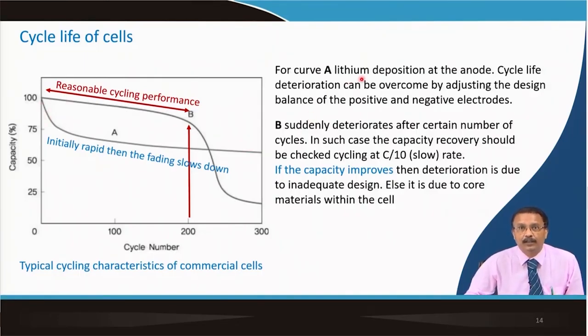Anyway, so for curve A, lithium deposition at the anode, cycle life deterioration can be overcome by adjusting the design. So, balance is important. That is, this is due to the balancing of the capacity. But when it suddenly deteriorates after a certain number of cycles, the capacity recovery should be checked, that is, whether at a lower rate again it goes back to its original value. If the capacity improves, then the deterioration is due to inadequate design, else it is due to the core material